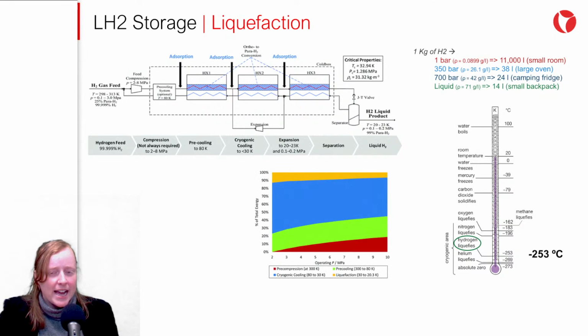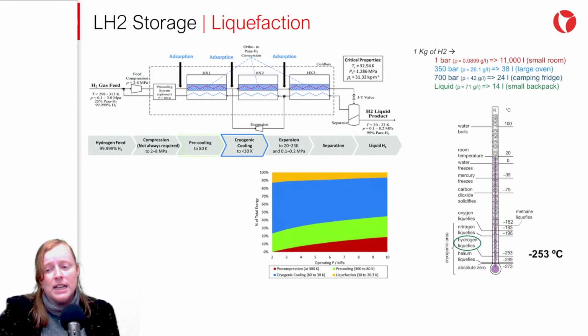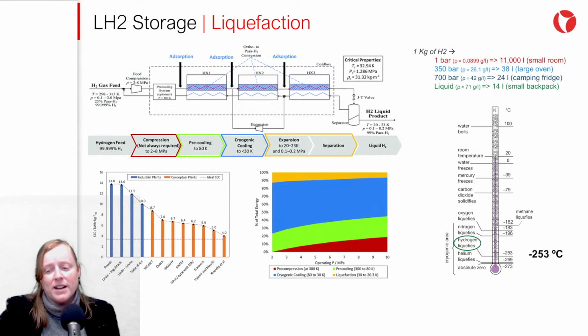This process is very energy intensive. As seen in the graph, most of the energy is consumed by cryogenic cooling. That is, the jump from negative 196 degrees to negative 253 degrees Celsius, followed by pre-cooling, pre-compression, and the final expansion and separation. Current processes have specific energy consumption well above the ideal consumption, although there are theoretical plant designs that would be closer to it.